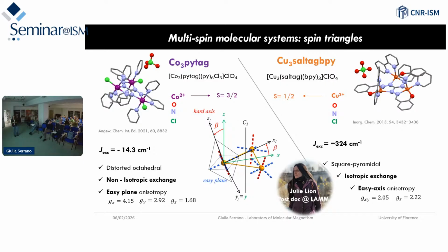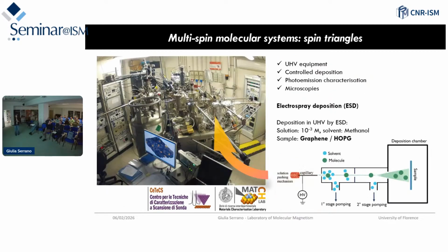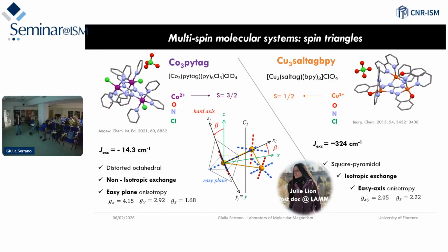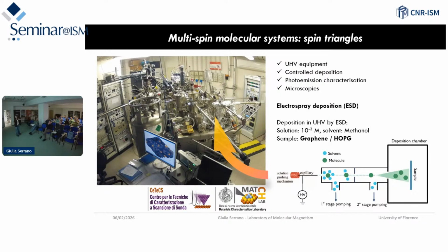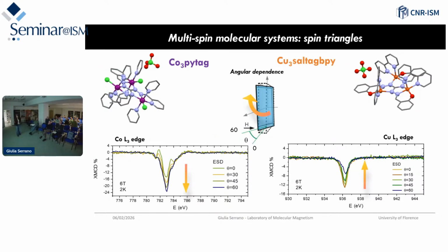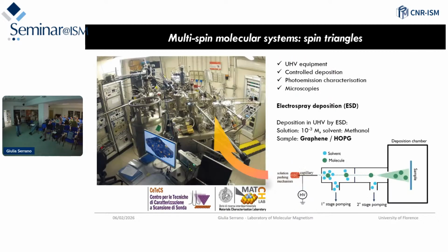The investigation of both compounds is important because the two compounds have really different magnetic exchange interaction strengths between the ions, so it can give us in the future feedback on the role of the surface on this exchange coupling. These are fragile systems because they are ionic compounds. This is the main molecular structure, but you can see that we have a counter ion, so we cannot sublimate this system, and we spray it on the surface by an electrospray deposition setup, in which we have a capillary that injects the solution through two different pumping stages to the sample.